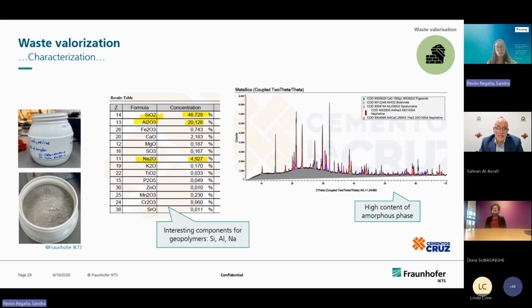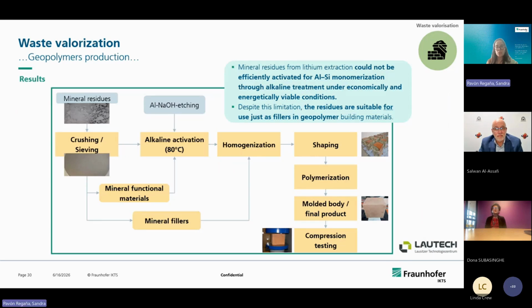Then what we did is a characterization of this lithium-free residue, and it looked really promising because silicon is there, aluminum is there, so interesting components for geopolymers. Then, in collaboration with another industry, so we are not talking about lab scale, we are going to validation scale. They already do some treatments: crushing, sieving first, then functionalizing the material with alkaline activation, and then homogenization, shaping, polymerization, and then making the molded body, and then the testing, so compression testing.